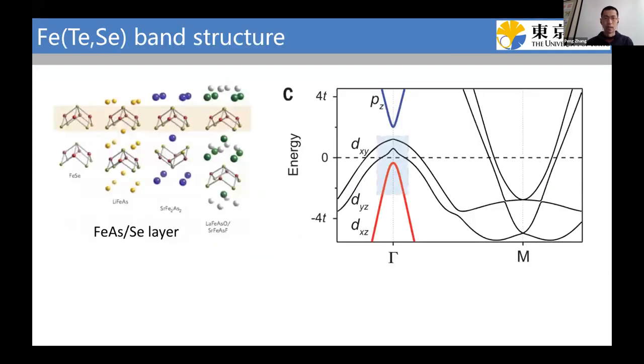This is a simple band structure for the iron-based superconductors. The band structure near the Fermi level mainly comes from iron 3d orbitals, from the iron arsenic or iron selenide layer. Before, people mainly resolved the 3d t2g orbital bands near the gamma point.